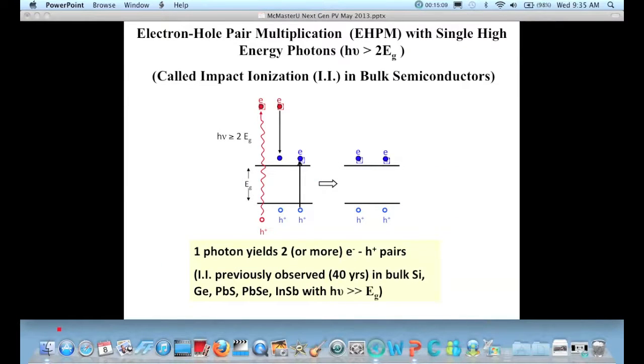So the idea that you can do this is old. It actually does occur in bulk semiconductors. It's called impact ionization, and it was studied 40 years ago in many bulk semiconductors. And in that case, to conserve energy, of course, the photon has to be at least twice the band gap. And this extra energy, which is in the form of kinetic energy of the electron and the hole, can, instead of cooling, which is emitting phonons and converting this excess kinetic energy into heat, do something more useful, which is to generate a second electron-hole pair.